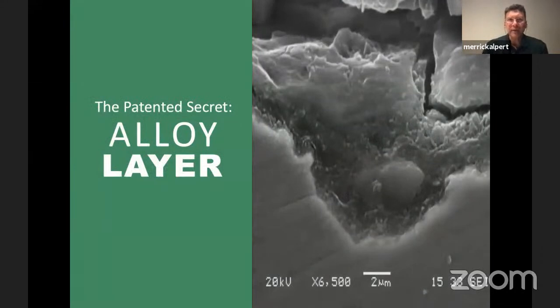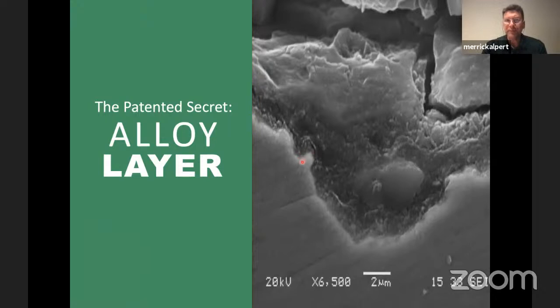The most important slide that I'm going to show you this evening is this slide right here. And I'm going to actually use the little laser pointer to show you it. This is a scanning electron microscope photograph taken at 6,500 times magnification. This is Eoncoat that has been sprayed onto carbon steel and then dried for a few minutes. So first you see the carbon steel at the bottom. You can see that typical grain pattern of carbon steel, if you're familiar with the way carbon steel will look under the microscope. Second, you see the dry Eoncoat up here. You see the typical indications of a ceramic, an acid-base ceramic, out here.